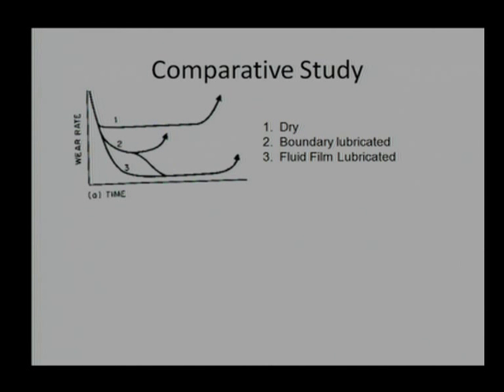Surfaces are completely separated by the fluid film. If we plot curves for these three conditions, one for dry, second for boundary, third for fluid film lubrication, then what kind of curves do we get for the wear rate? If I plot wear rate with time, this clearly shows a bathtub curve. Wear rate decreases, remains stationary, and then goes up after a certain duration.